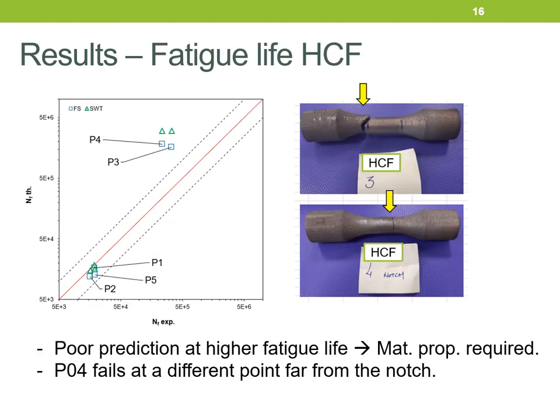For the high cycle fatigue test, the predictions of both models are poor, probably due to the material properties characterization. For sample four with notch, the crack starts from the hole but failure occurs outside it, so those values were again rejected. The crack angle in this case was 68 degrees, and Smith-Watson-Topper again returns a better angle estimation.